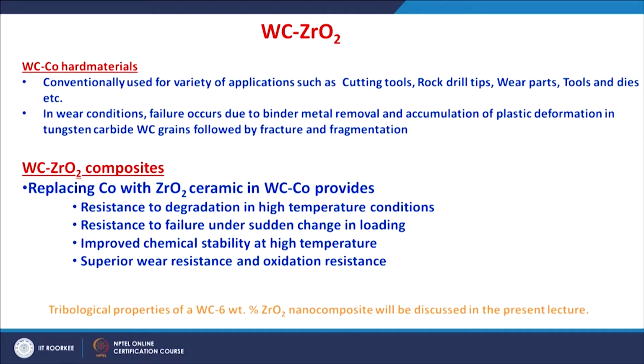Those conditions are generally encountered in high speed cutting tool applications. We can also have an improved resistance to failure under sudden changes in loading, and improved chemical stability at high temperatures, because zirconia is chemically more stable at high temperature than cobalt or steel. In turn we get superior wear resistance and superior oxidation resistance. So the degradation of the material, through metal binder removal or by fracture or fragmentation, can be reduced if you go for a ceramic additive rather than the cobalt binder.